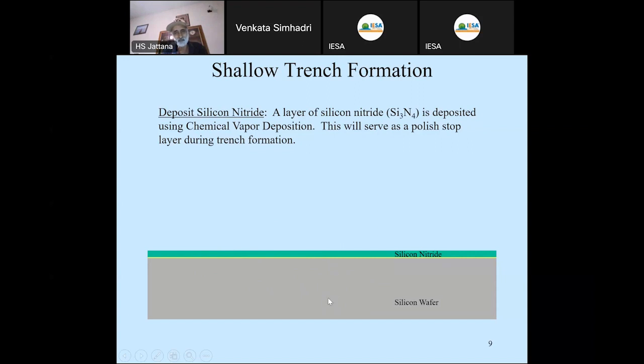The rest is there because you have to handle the wafer; you cannot handle a very thin wafer, and the wafer has to see temperatures like 1000 degree, 1100 degree centigrade. So to give good mechanical strength, this kind of thickness is kept. Flatness of the wafer, resistivity of the wafer. So we are using resistivity 1 to 50 ohm centimeter wafers, and there are certain epi wafers also, n on n and n on n plus plus. They have their own advantages.